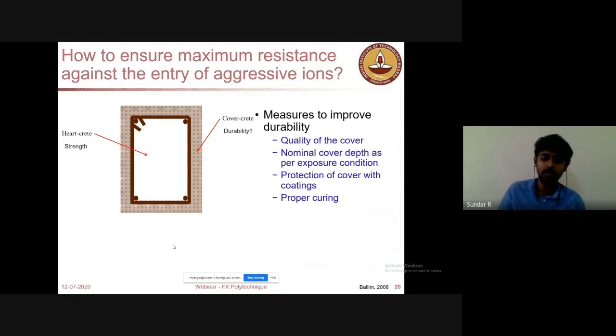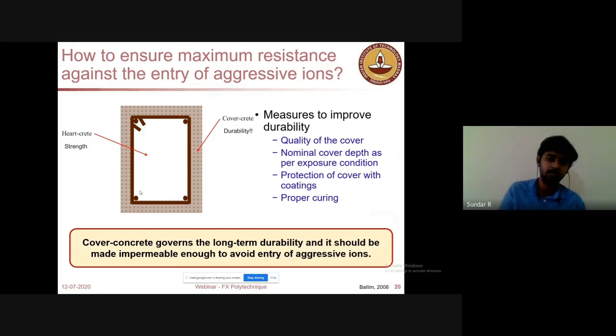So to improve durability, we should have a quality cover. The strength of the concrete pertains to the heart concrete, the inner portion which is bound by reinforcement in the RCC, and cover concrete is the governing factor for durability. So the concrete should have a very good quality cover, and the nominal cover necessary for the specified exposure condition, and it should have protective coatings otherwise. If there is inadequate cover, you should have a protective coating, and it should be properly cured. For example, concrete with SCM should be cured for a longer time. So we have to make this cover very high quality, and it should govern the long-term durability.